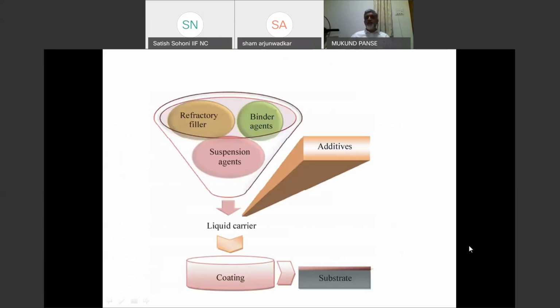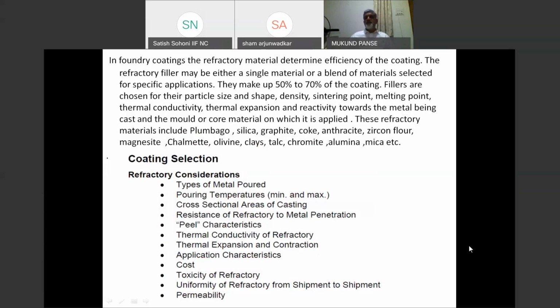So basically, refractory filler, binder and suspension agent, these are added to the liquid carrier and additives are added, and so the coating is ready to be applied to substrate, that is sand or core mold. The refractory material is the base of a coating, which determines how efficient the coating is. Normally, in a refractory coating, the refractory particles constitute 50 to 70%. Its particle size, shape, density, sintering point, thermal properties, chemical properties, expansion characteristic, reactivity, etc. are all considered for deciding the exact appropriate coating for a proper application.